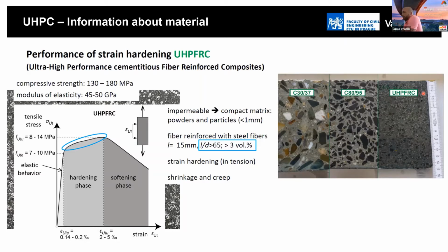And this is very important for the long-term behavior, not long-term behavior due to the creep or the shrinkage, but long-term behavior due to the durability, especially the effect of chemical attacks from the environment. UHPC is closed, so for example, it is not necessary to produce a waterproofing surface on these elements. Also, you could reduce the distance between the bars and the sides of the concrete. And again, you could reduce the dimensions, because very often the dimensions of the concrete elements are affected by the dimension of the cover of the reinforced concrete. So if you could reduce the size of the cover, you could reduce the dimension of the concrete element.